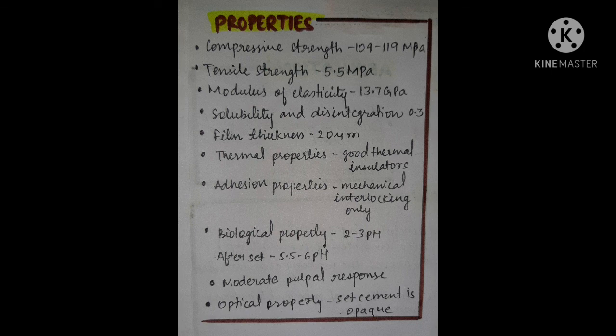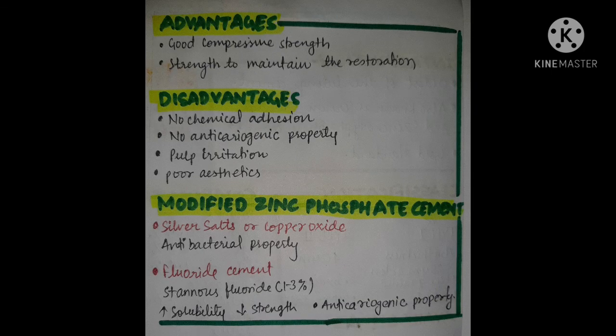In biological property, the pH is 2 to 3, and after set it is 5.5 to 6 pH. It is a moderate pulpal response. Then in optical property, the set cement is opaque. Then advantage, it has good compressive strength and strength to maintain the restoration. Then disadvantage, no chemical adhesion, no anti-cariogenic property, pulp irritation, and poor aesthetic.